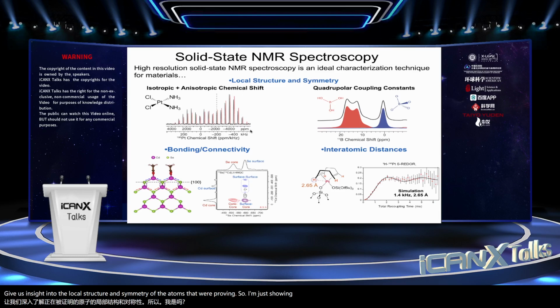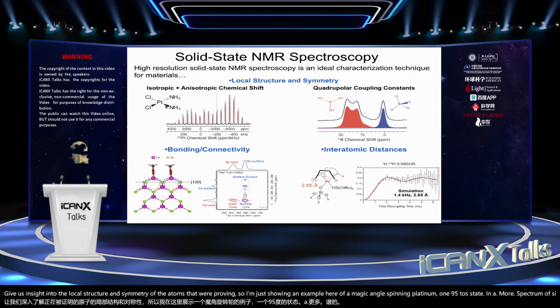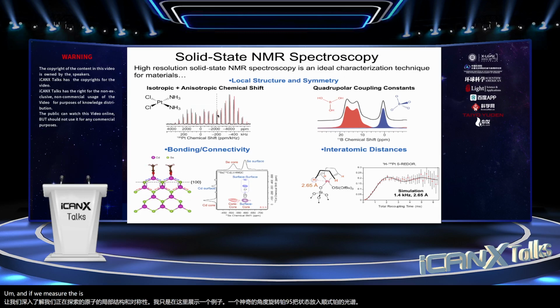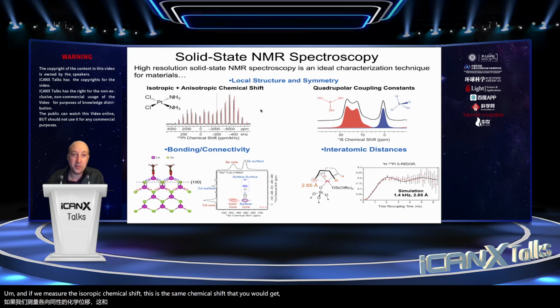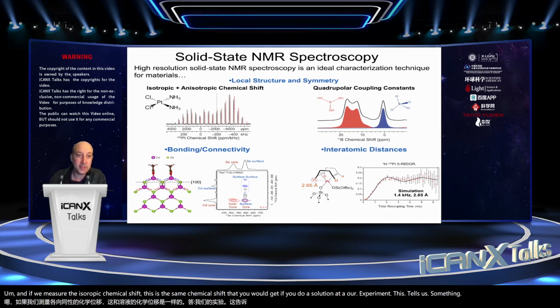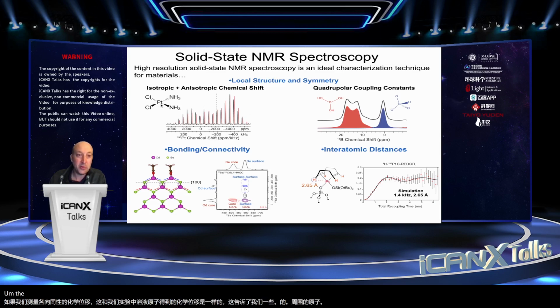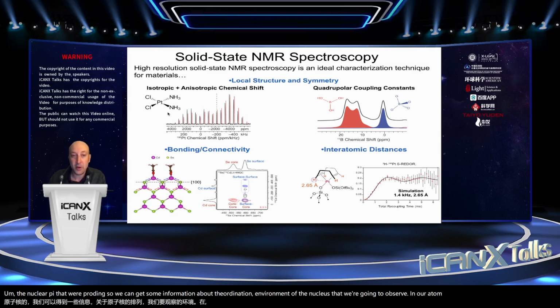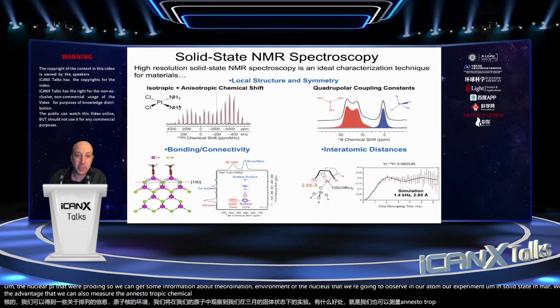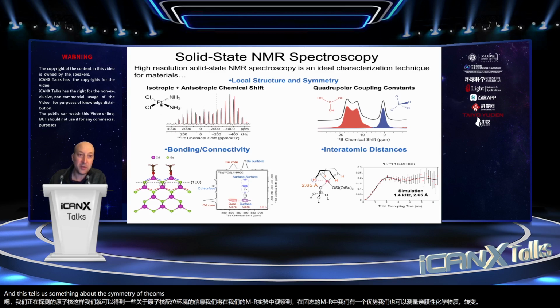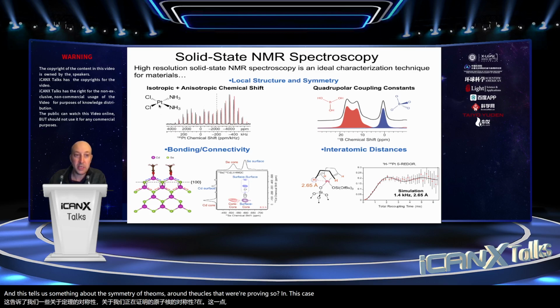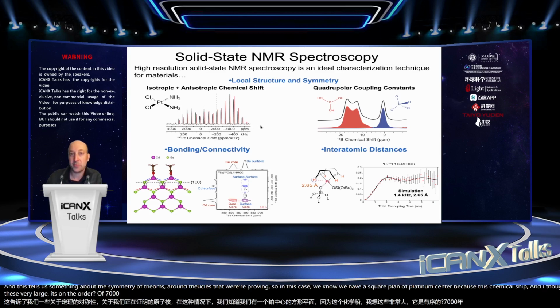So I'm just showing an example here of a magic angle spinning platinum-195 solid state NMR spectrum of cisplatin. And if we measure the isotropic chemical shift, this is the same chemical shift that you would get if you do a solution NMR experiment. This tells us something about the atoms that surround the nucleus that we're probing. So we can get some information about the coordination environment of the nucleus that we're going to observe in our NMR experiment. In solid state NMR, we have the advantage that we can also measure the anisotropic chemical shifts. And this tells us something about the symmetry of the atoms around the nucleus that we're probing. So in this case, we know we have a square planar platinum center because this chemical shift anisotropy is very large. It's on the order of 7,000 parts per million.